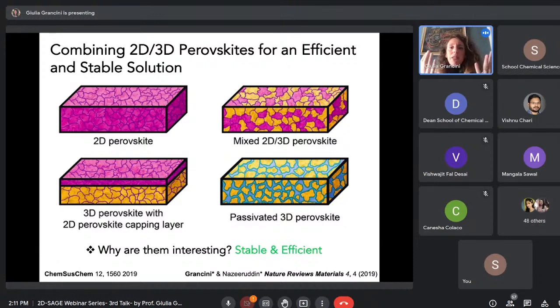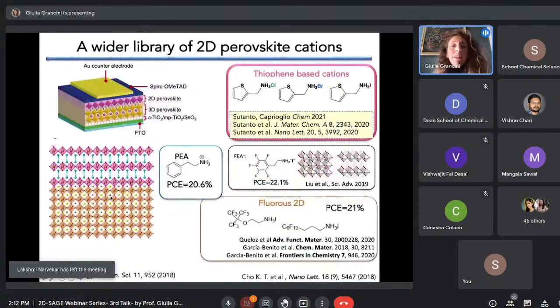So when you take the two components, first thing you can do is mix them together, like in a blend, like in a heterojunction, forming this mixed 2D/3D perovskite. Or you can use a very tiny amount of 2D to just passivate the grain boundaries of the perovskite. Or alternatively, you can form the so-called layer-by-layer structure, where you have a 2D perovskite layer on top of the 3D. In particular, this layer-by-layer structure has been the one that was first developed in 2018. Here you can see some examples of publications in an NIP configuration, where you have the 3D and then on the top the 2D perovskites.